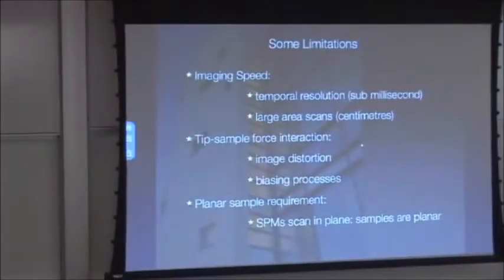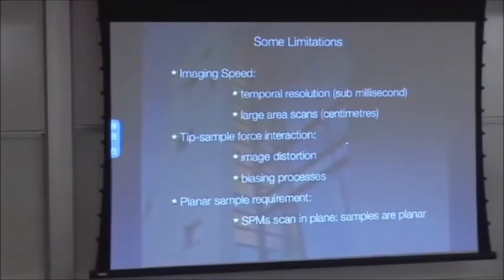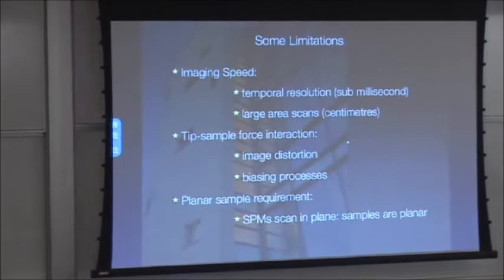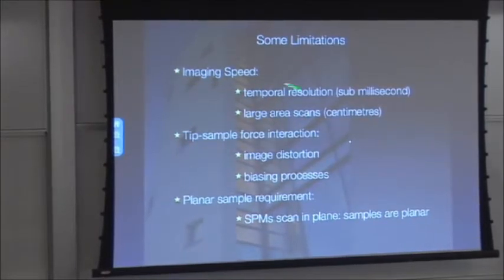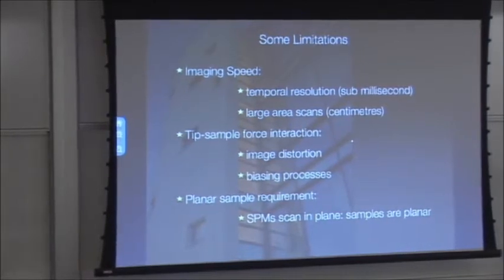So that was the good news. The bad news is that the imaging is very slow. If you've ever done atomic force microscopy, you know it takes a minute or so, maybe up to 5 or even 10 minutes, depending on the sample, to get one image. And so what we need to do is go faster. We'd actually like to be going at sub-millisecond per image, if we could, in order to capture some biological processes.